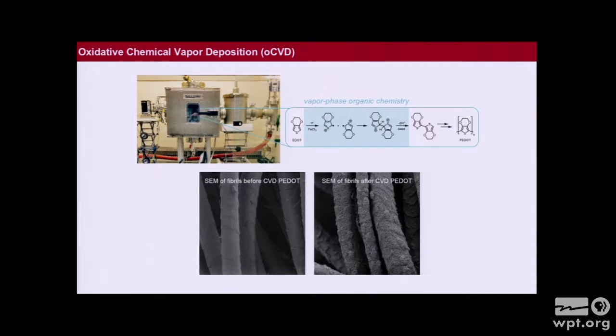But what you see is the PEDOT conformally coats each one of the fibers. And where there is an empty space between the fibers, you don't see any polymer. You follow the curvature of the fibers itself. If there is a break in the fiber, you see that as well.